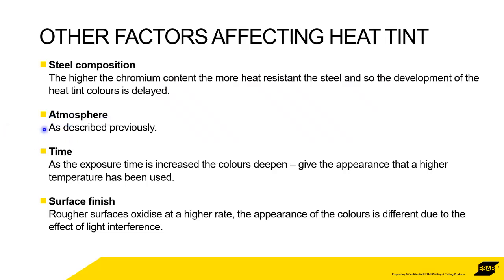Atmosphere obviously helps. So oxygen rich means you're going to get heat tint. Exposure time causes the colours to deepen. So multi-pass welds, where the heat affected zone is repeatedly being heated up, will deepen the colours, and it gives the appearance that a higher temperature has been used, so it can catch you out maybe. And surface finish, so the rougher surfaces oxidize at a higher rate.